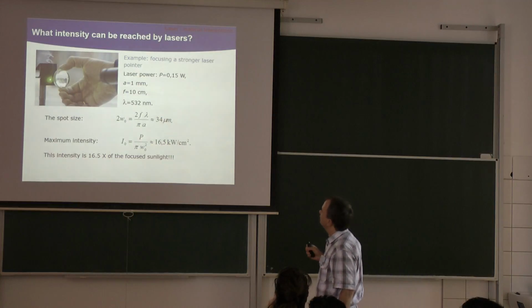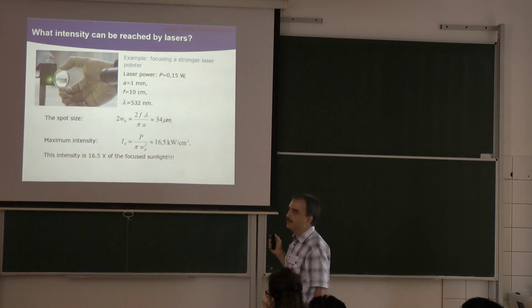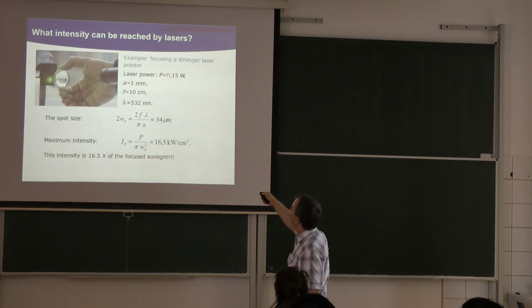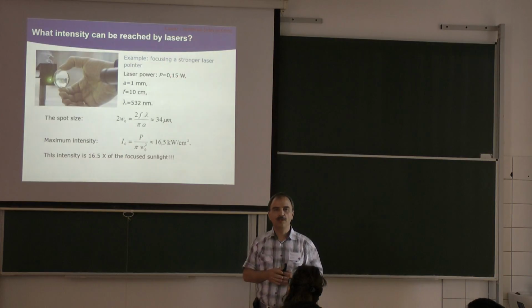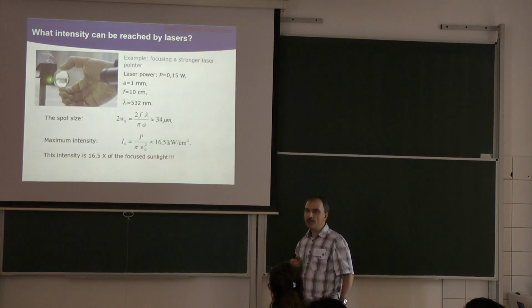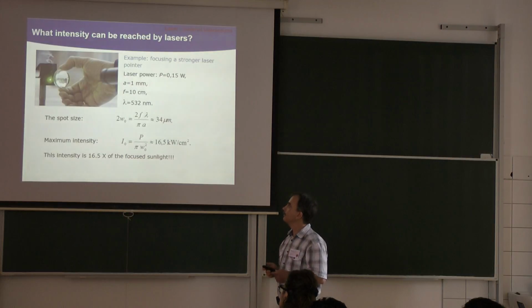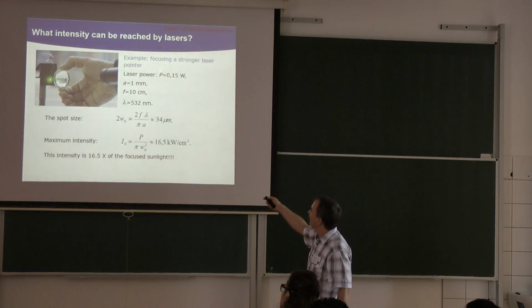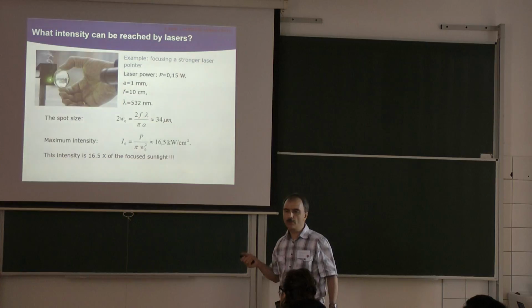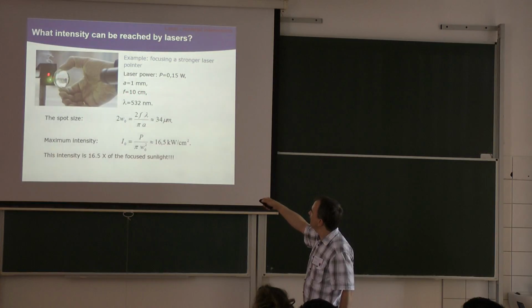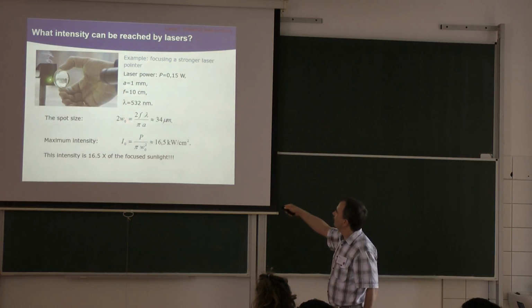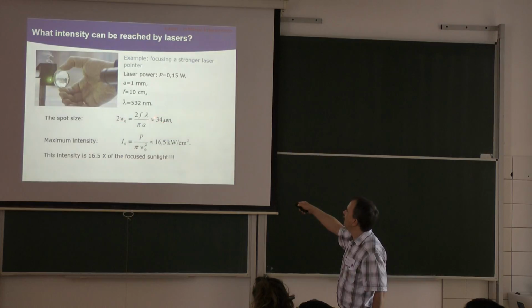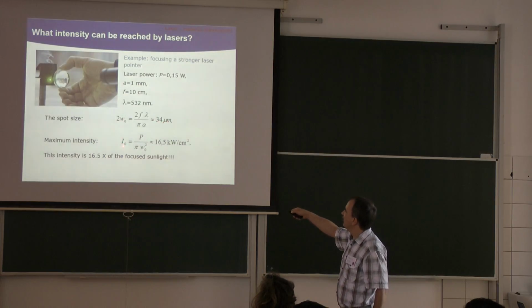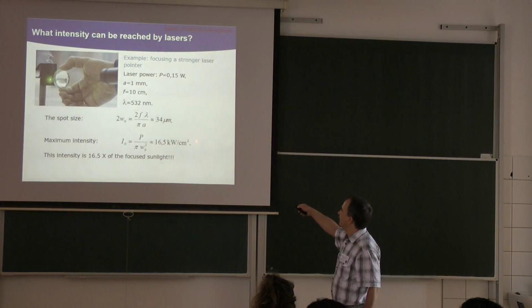Now we do this calculation, and we see the parameters of this simple experiment, where we have a power of 0.15 watts. This is already a high power. You can have this even with a continuous laser, and it is 2 orders of magnitude higher than, for example, this laser. The aperture of this laser is 1 millimeter. The focal length of this lens was 10 centimeters. Here we have the wavelength. We can calculate the spot size. The beam waist radius was approximately 30 micrometers. So we can calculate the maximum intensity, which is 16.5 kilowatt per centimeter square.